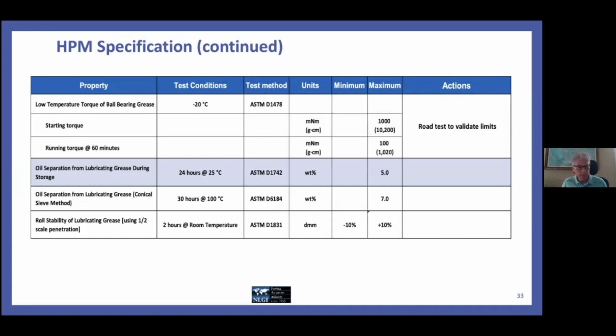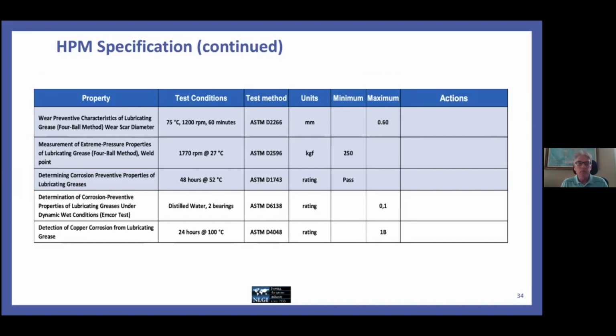Okay, the final page of the HPM Core Specification. The first 3 tests are in GCLB, but with different limits. The first test is the 4-ball wear test, standard conditions, with a 0.6 millimeter scar maximum. The 0.6 is the same as today's specification in the LB specification, but it is more severe than the GC specification. Then the next test is the extreme pressure version of the 4-ball test, with a specification of a 250 minimum weld load.